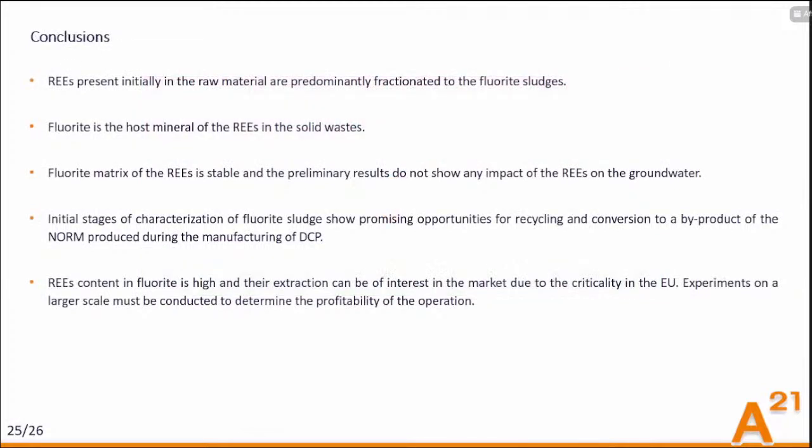And to conclude, all the rare earth elements which were inside of the raw material were actually fractionated to the solid phase, to the fluorite sludges. As I mentioned, the fluorite is the host mineral of the rare earths inside, which is quite stable. And well, the preliminary results don't show any environmental impact of the rare earth elements on groundwater. And since the fluorite is quite stable, we don't think there will be any impact.